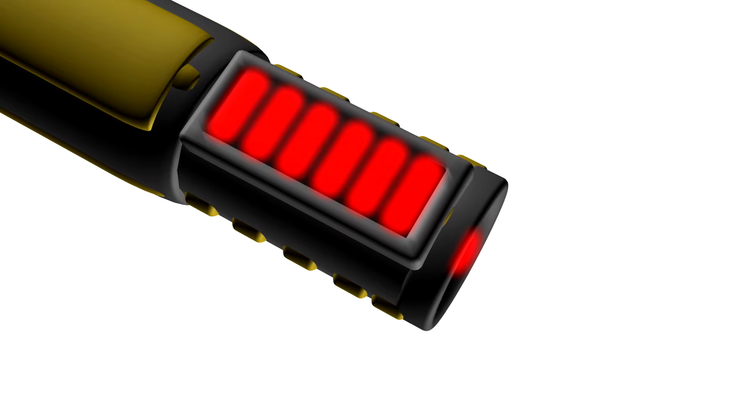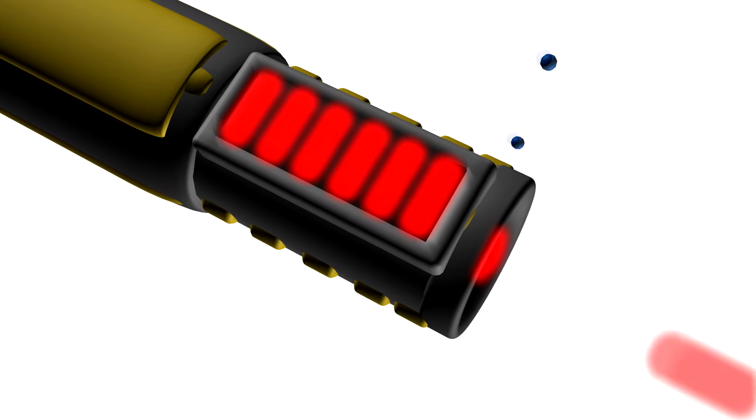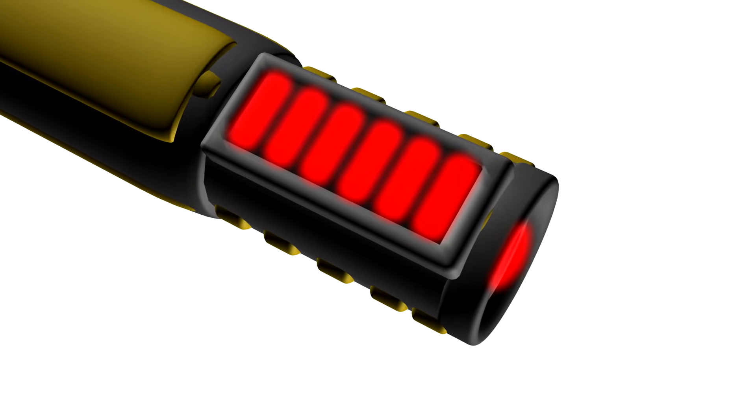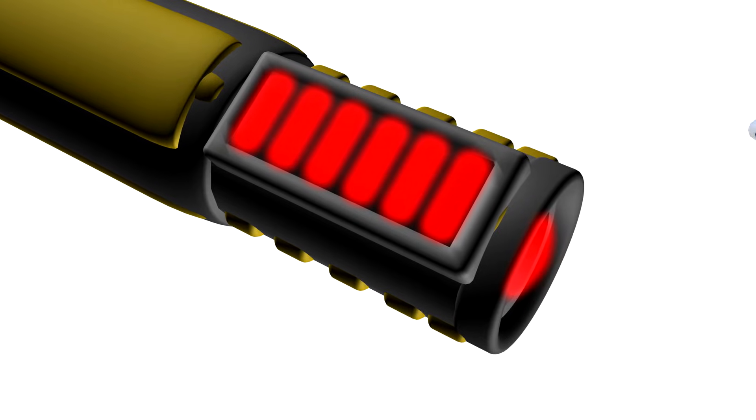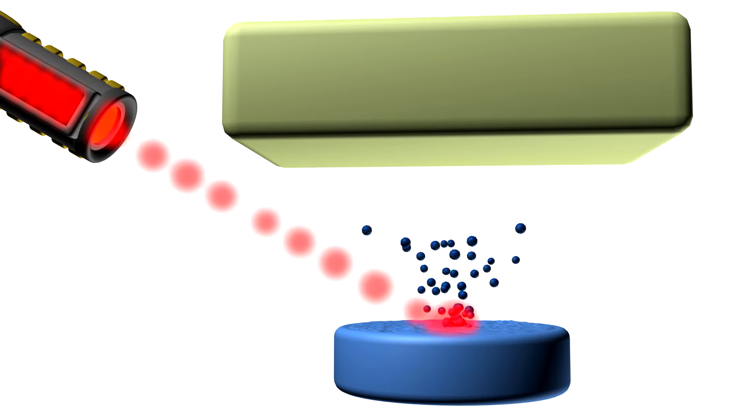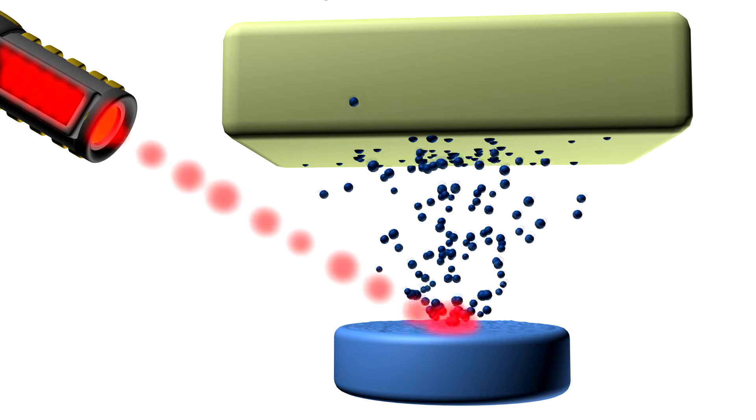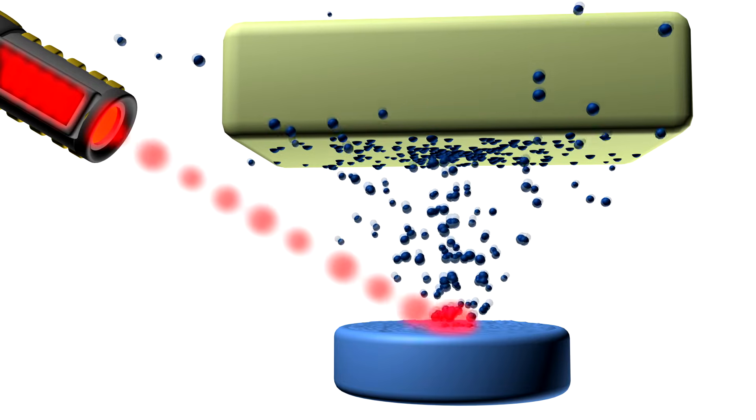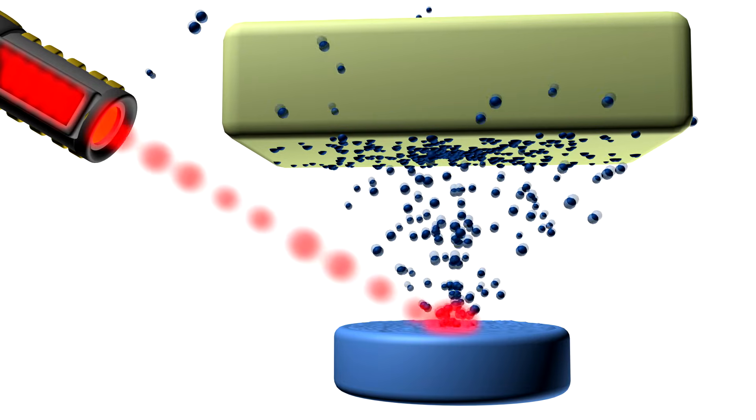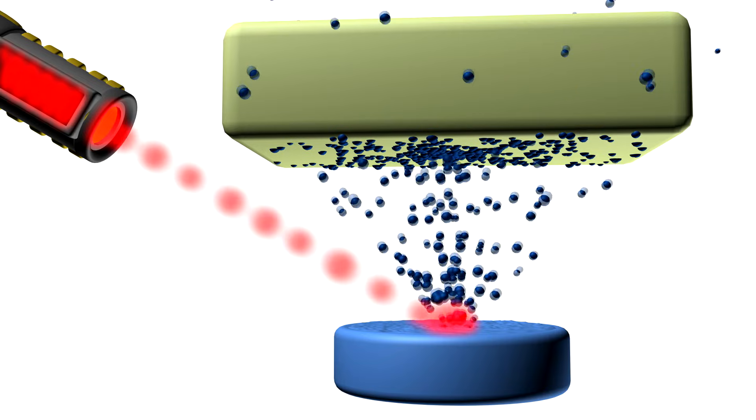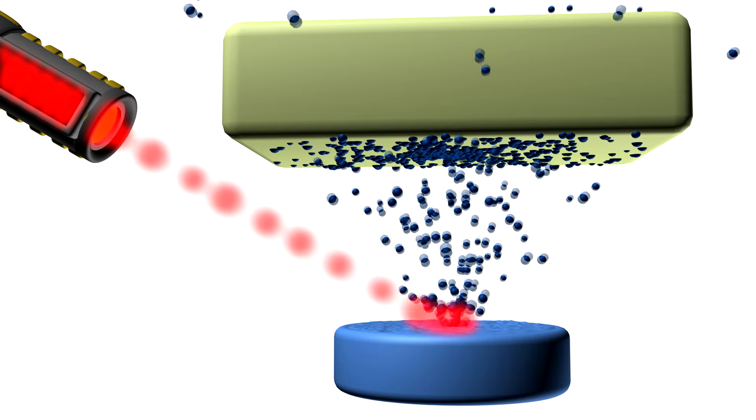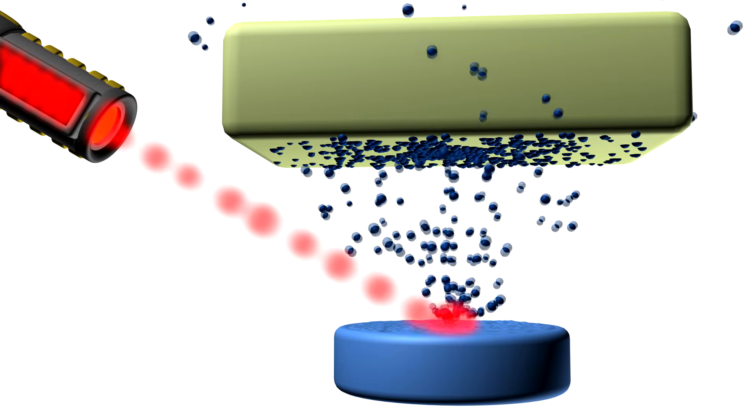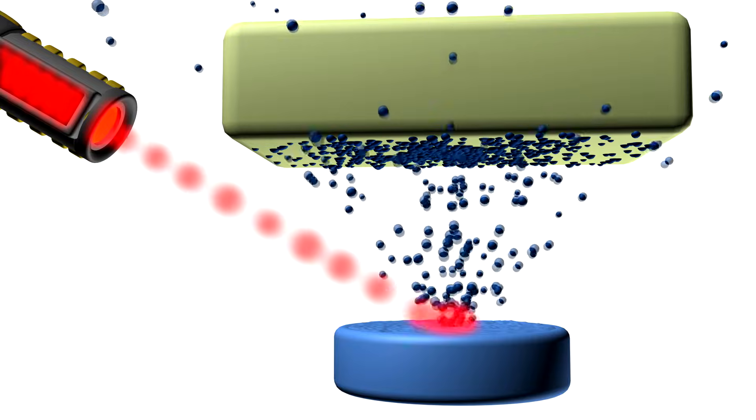The intensity, wavelength and length of the laser pulses also have a significant effect on the excitation mechanism that takes place on the target surface. For instance, using a laser with short pulses, shorter than one picosecond, electrostatic ablation occurs, in which case the electrons that hold the material together are excited so fast that they leave the material, resulting in an explosion of the small amount of target surface.